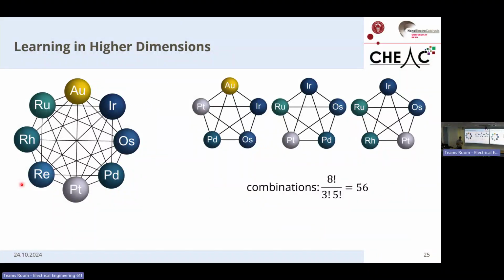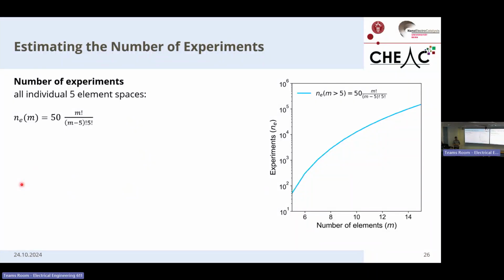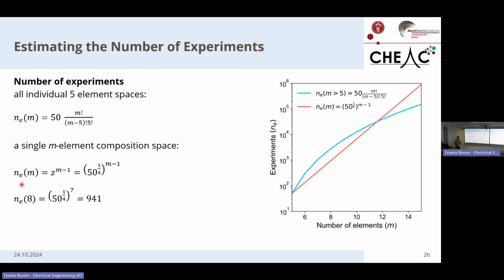So if we now take these 50 experiments as a guideline for the number of experiments we need to study an individual 5-element space, we end up at 2,800 experiments that we need to invest to study all possible combinations. So this has to do with the fact that if you go up in dimensions, the number of experiments is growing according to the combinatorics. So you calculate the number of spaces encapsulated. But the number of experiments that we need to study a combined space grows exponentially, and that results in this red curve. So if we want to study an 8-element space with the same information density as a 5-element space, we only need 940 experiments. So we save 1,900 experiments by studying everything together.